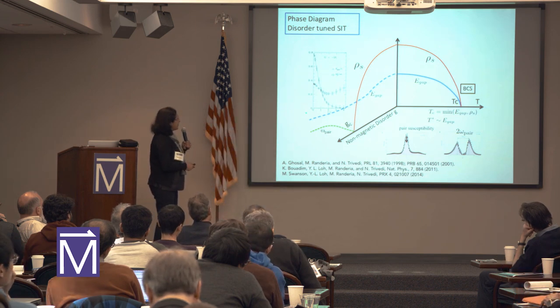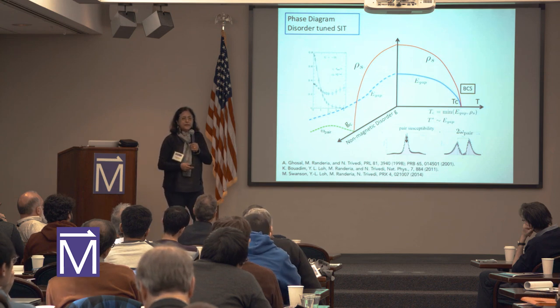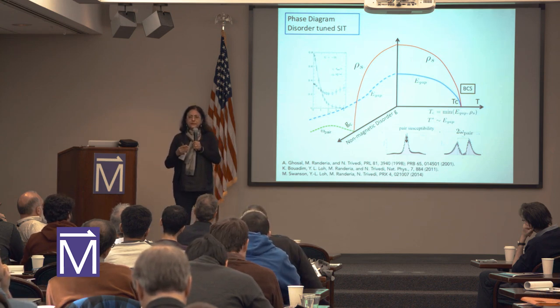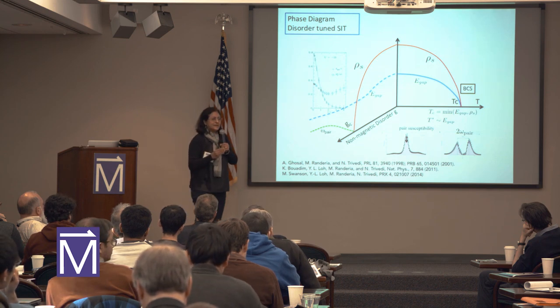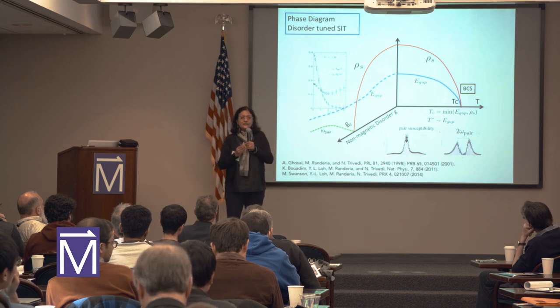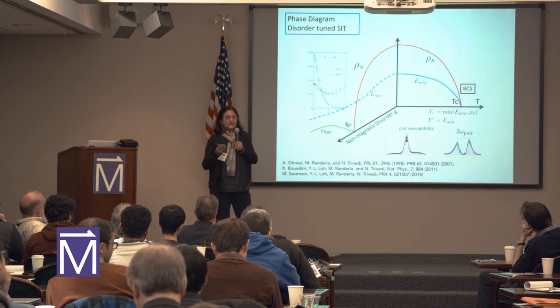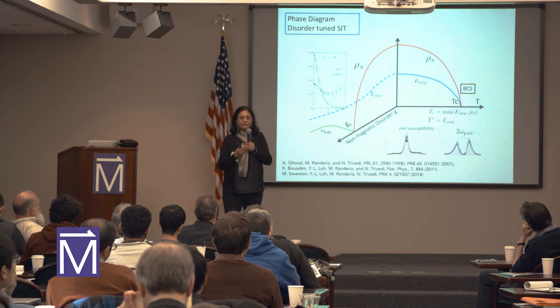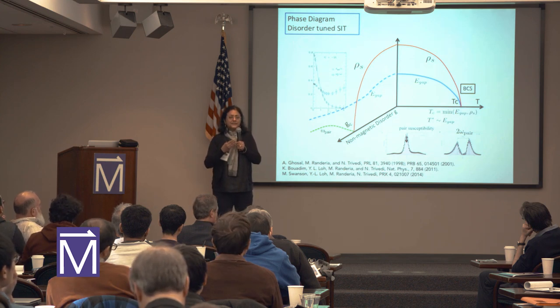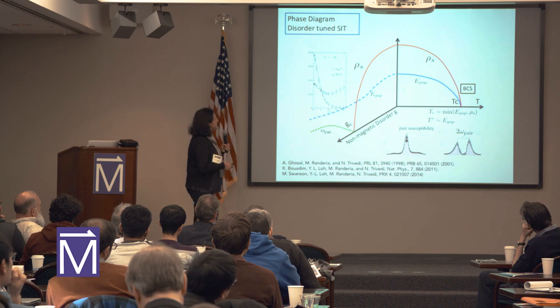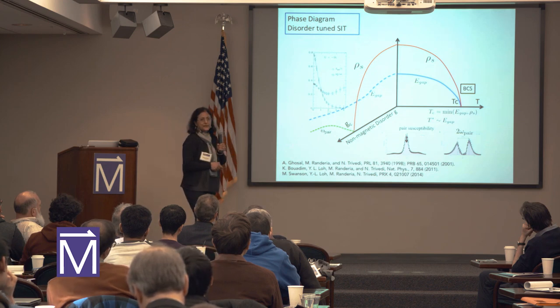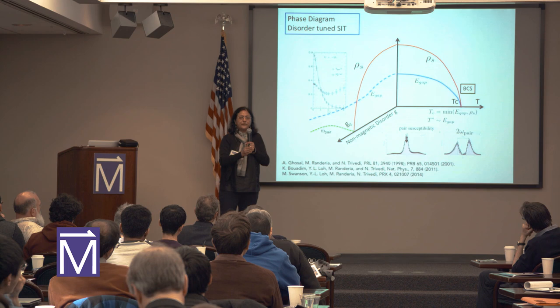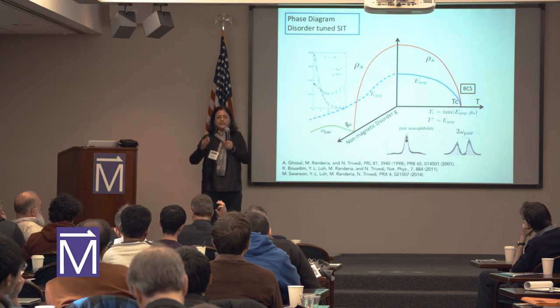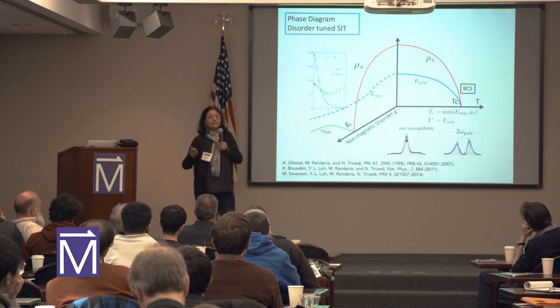Now, furthermore, we also went on to study, as you know, that in a superconductor there is a delta function peak at zero frequency. And this essentially describes the accelerating fermions. And as you add disorder, the strength of the peak is essentially given by rho_s, right? So there is a peak at zero frequency, then there is a gap above that, and then the broken pairs beyond some gap energy.